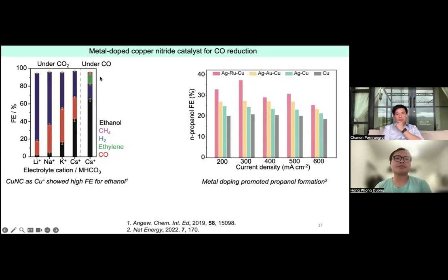Based on the previous report, in our lab we had before the thing called copper NC. What it is, in fact, is single atoms of nitrogen and carbon, and this makes a network, and then you put the copper onto it. It was also a work of one of the postdocs in my lab before, and in this case, the valence of copper was like copper 1+, and this compound was very good to make ethanol. But the important point here is also the nitrogen: the presence of nitrogen doping as a heteroatom was very significant to get the ethanol here.